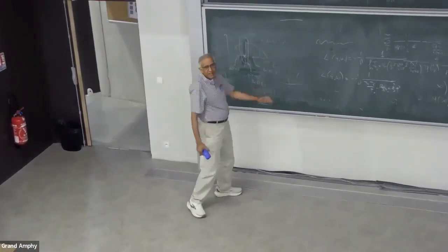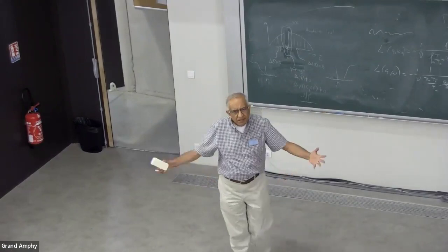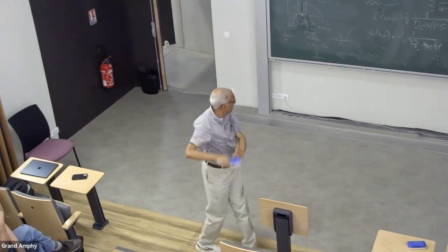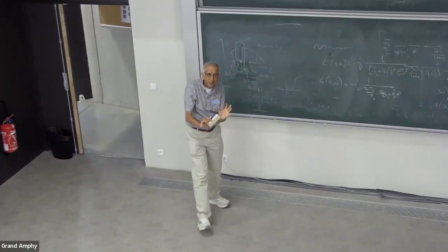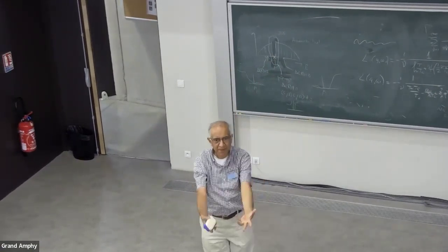What lies at very high energies in an Anderson insulator? States which are living high on top of hills. So they're empty. That's why the chemical potential is here. Beyond the chemical potential, you can have particle hole mixing and get pairing. The only thing is, this is all happening in a highly inhomogeneous way, which we would have never guessed unless we did the Bogoliubov-de Gennes calculation.